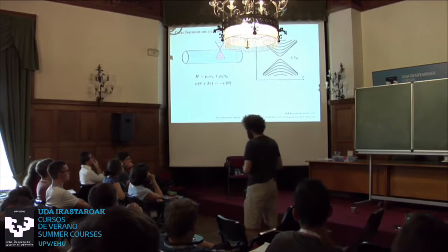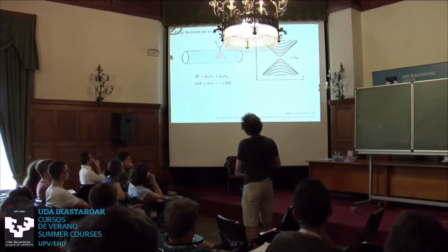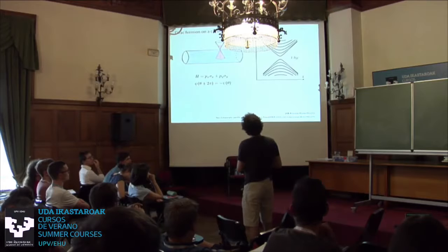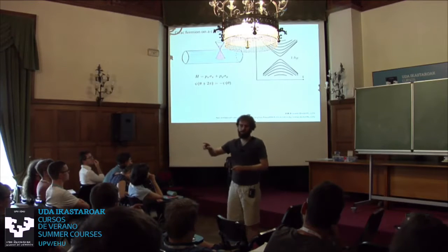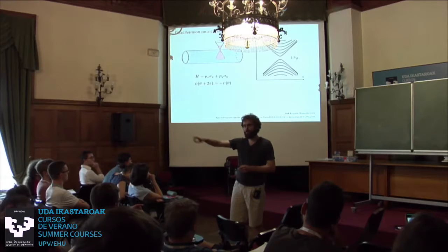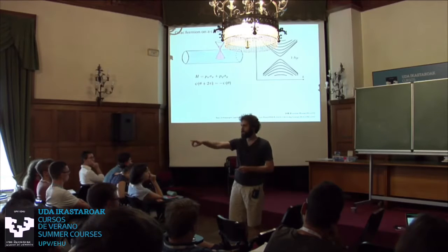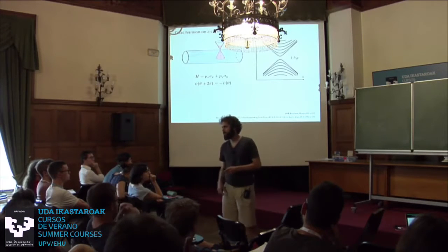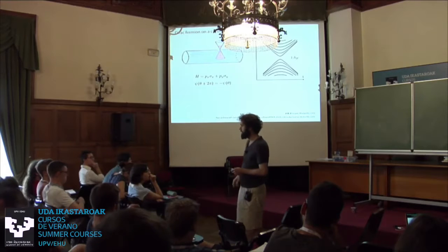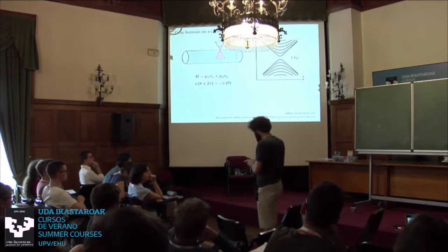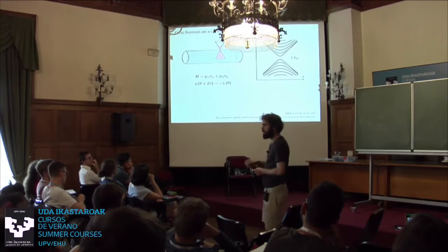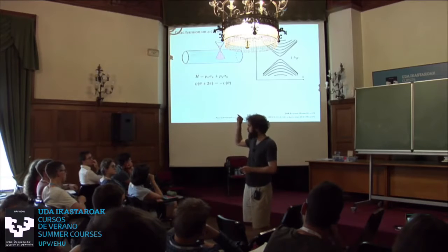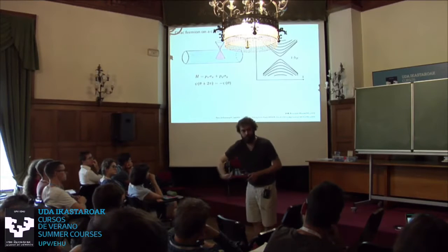And the reason has to do with the fact that this Dirac fermion that is on the surface here, its momentum is locked to the spin. This means that if the momentum points in this direction, the spin points in this direction or so. If it points in this direction, the spin follows. So if I now think about what happens as I move around this surface, the momentum goes in a circle.